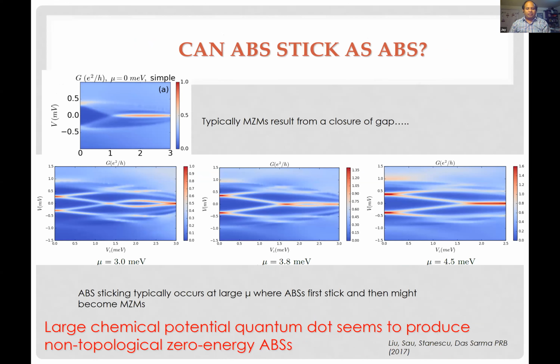So what can happen, and we did some theory simulations: when we raise the density of electrons with the increasing magnetic field, we see that there are subgap states in the superconductor called Andreev states. As the magnetic field is increased, they can cross, because one of these Andreev states has spin up and the other has spin down. The magnetic field makes them change in opposite directions, so they cross. Because of particle-hole symmetry, which is a fundamental symmetry of a superconductor, they tend to stick at zero depending on the parameters. And if I increase the chemical potential, for reasons I can't explain in detail here, they end up completely sticking and looking a lot like Majoranas, even though they're not Majoranas.